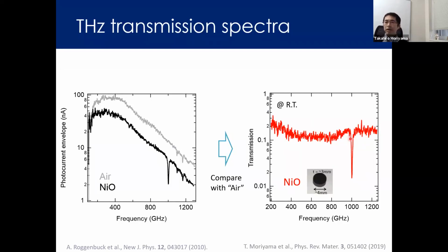So this is a typical terahertz transmission measurement result for antiferromagnetic nickel oxide. The vertical axis here is the photocurrent detected by the detector, which is basically proportional to the transmitted terahertz waves through the sample. You can see a very sharp dip right at 1 terahertz. From this data we obtain the terahertz transmission of the nickel oxide by comparing this raw data with a measurement of the air, without the sample. And after processing the data, we can see the clear absorption peak at 1 terahertz, which comes from the nickel oxide antiferromagnetic resonance.